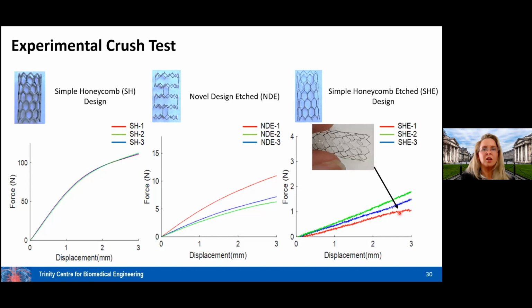So it's worth noting this lower one here, actually one did have a fracture, but that was just one out of all of the stents that we printed, and in fact had a fracture on that strut. And it does impact the radial stiffness, of course, but overall we found the etching was very successful for reducing the strut size, improving the surface roughness, and also controlling the radial stiffness. So if we want something more conformable, less stiff, we can definitely do it by etching away.